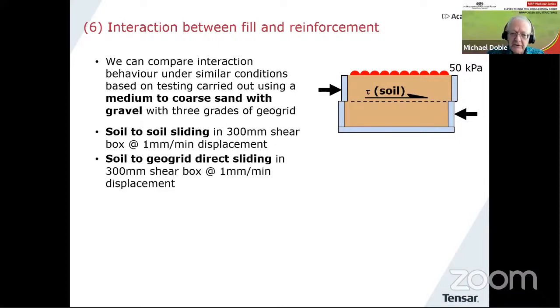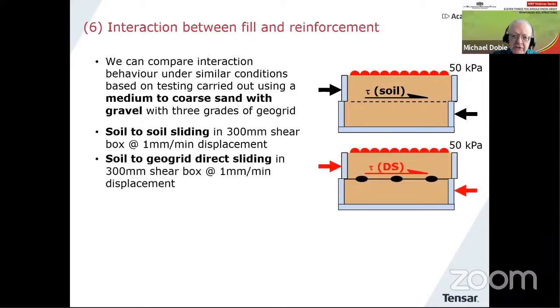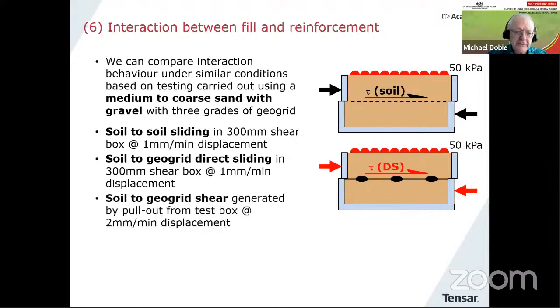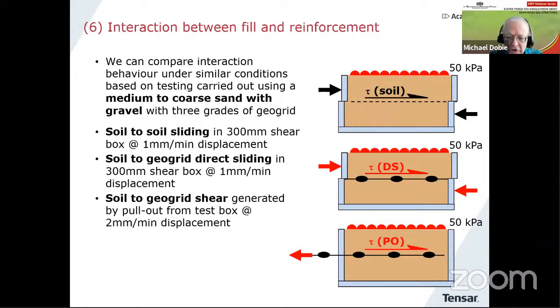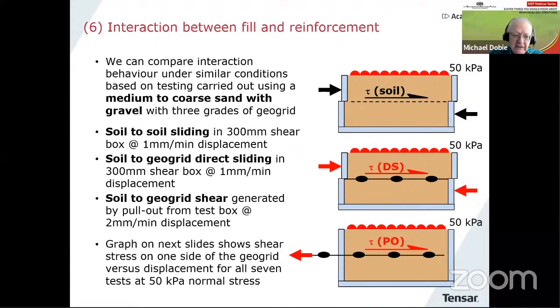We then do the one with the geogrid in it, which looks like this. So now it's the same basic test, except now we have the piece of geogrid clamped at the midpoint to give us the effect of sliding over geogrid rather than sliding over soil, or sliding over geogrid and soil. And those are both carried out at 1 millimeter per minute because it's a coarse soil. And then finally, we have the soil to geogrid shear generated by the pull-out test. Now, this is a slightly different situation because you have shear going on both sides of the geogrid. But I'm just going to show you a comparison of the shear resistance or shear stress generated on one side only in each case. So we look at that in the graphs that follow.